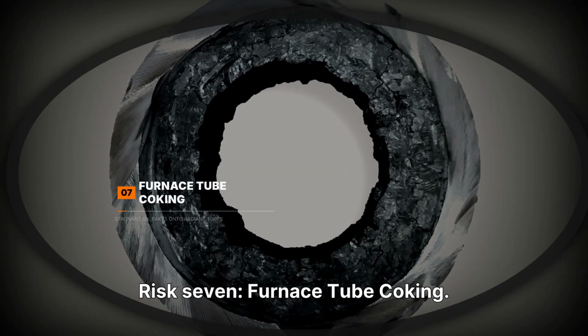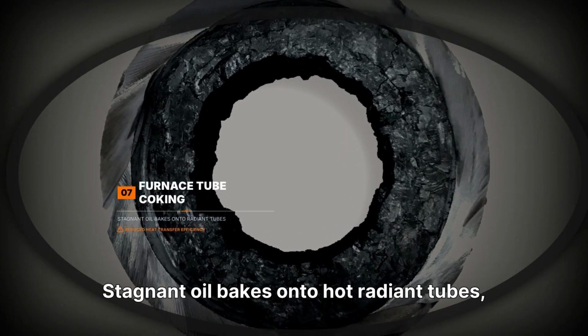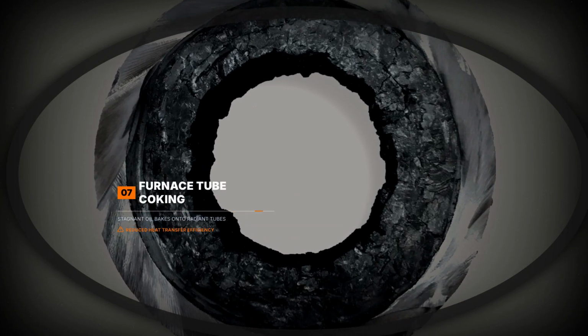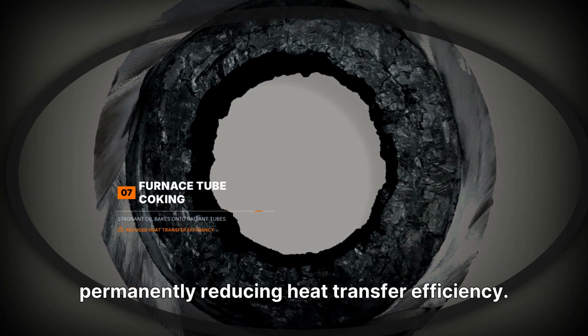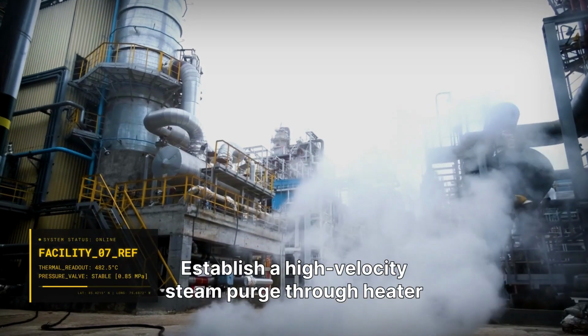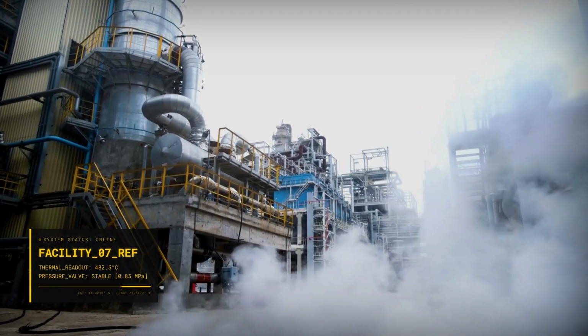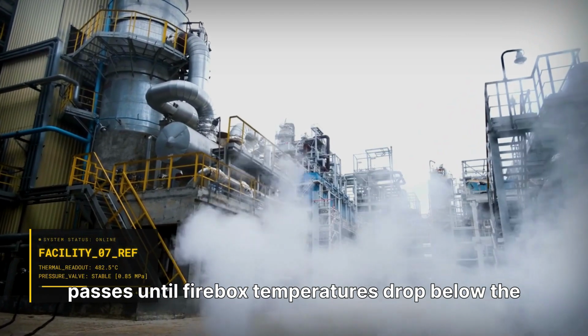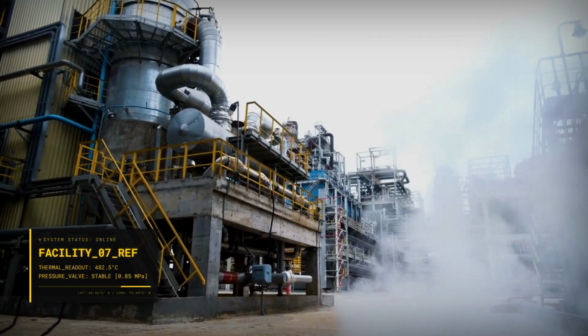Risk 7. Furnace tube coking. Stagnant oil bakes onto hot radiant tubes, permanently reducing heat transfer efficiency. Establish a high-velocity steam purge through heater passes until firebox temperatures drop below the coking threshold.